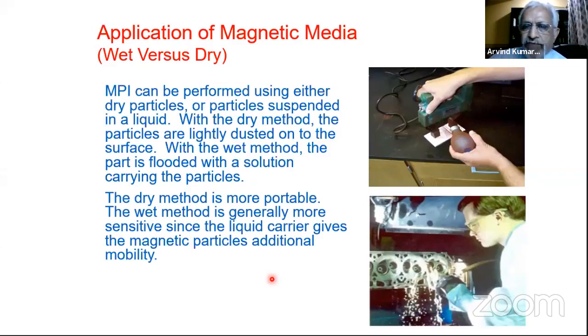Now, generally for dry methods, you must have seen that the NDT operator will first, if they are doing it on the weld, put a white coat, and then over that they will magnetize and put colored particles, either red or gray, which are mixed in a medium. Where there is an indication, with a good contrast, you will get white and red contrast, and you will be able to pick up the indication. And that paint is hardly about 15-20 microns.